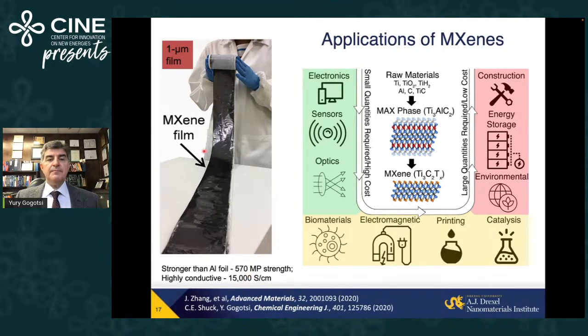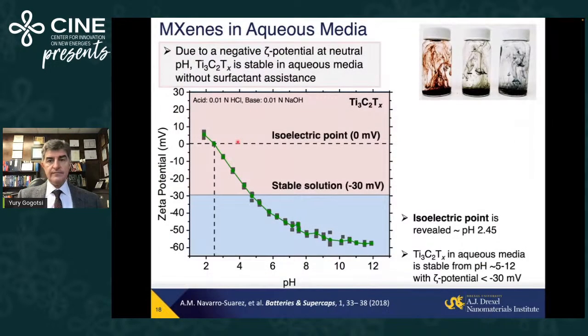Imagine, for example, a battery current collector with 1 micron thickness instead of 10 micron, because you cannot process metal foil in this thickness. How much of a difference it can make in weight and size of our lithium-ion batteries. It's possible because, again, of the high negative zeta potential of MXenes, lower than minus 30 millivolts at neutral pH, so it can form a stable solution in water.